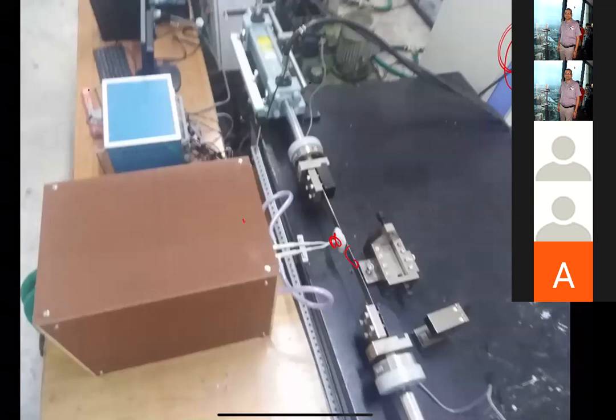This particular facility is in working condition, but at present we can calculate coefficient of friction only above 700 degrees centigrade, up to maybe 1200 degrees centigrade. Below 700 degrees centigrade, we don't have a sensor, because our fabricator said that due to the lockdown, which started in February in China, we are not able to get our sensor. So once all this COVID situation subsides, we will be able to test below 700 degrees centigrade. This is a new facility in our laboratory.